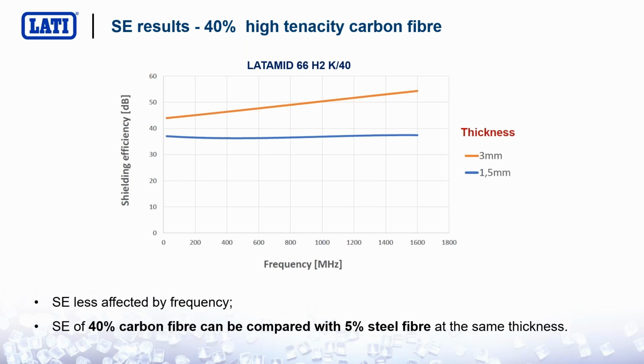This is a very important result because normally we use carbon fibers for tribological applications, for electrically conductive applications, for structural applications, but we never suggested carbon fiber for EMI shielding applications. This graph here shows that carbon fibers can provide very nice performance also from a shielding point of view, and it is evident that the dependency of the shielding efficiency on frequency is not as complicated as with steel fibers. This is also very important because we are going to see in the next slides that this result suggested another experiment.